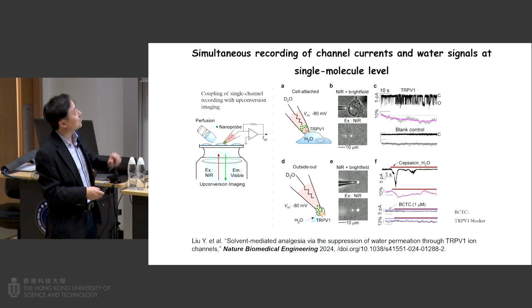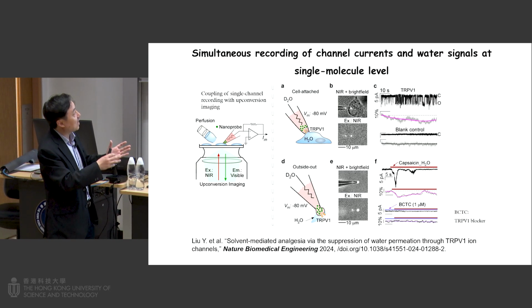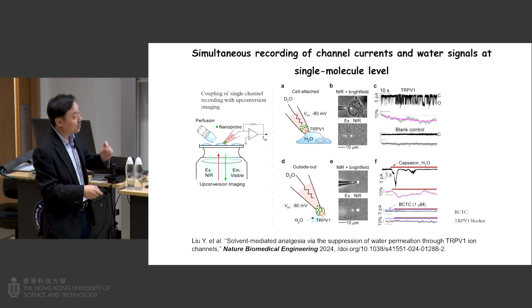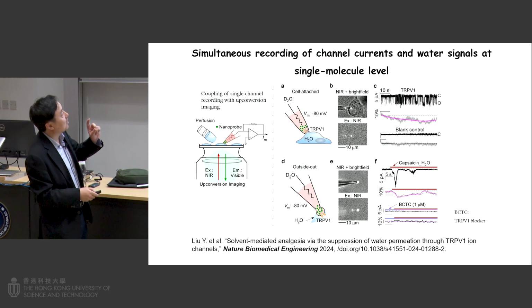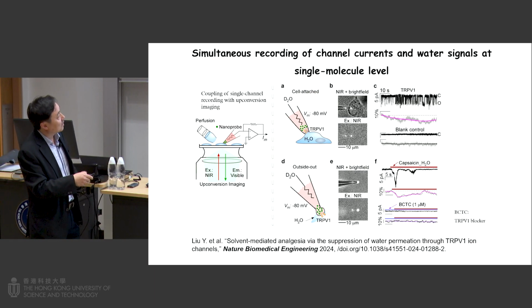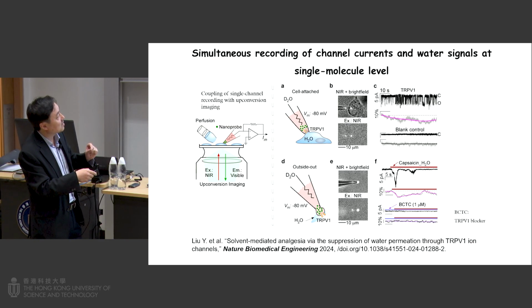So we actually achieved this. We can simultaneously record the channel current and also water signals. We can do this at the single ion channel, single molecule level. It took us a few years, using this setup, with the micropipette to connect a single ion channel. Then we place the particles within this micropipette. If the ion channel opens, you can see the D2O is the solvent in the micropipette. Once it opens, the water comes out, then the luminescence is quenched.